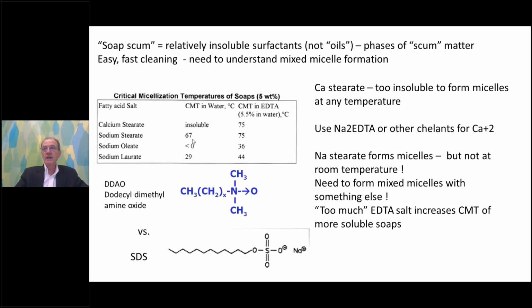So typically we formulate our soap scum cleaning products with some other surfactant because we're trying to form mixed micelles with the sodium stearate that we're trying to produce. And so we might use something like an SDS or an amine oxide. We can't arbitrarily turn up the amount of EDTA either because it's a salt. And if we arbitrarily add too much, we can actually increase the CMT of the shorter chain soaps like sodium laurate or the more soluble soaps like the oleate, which is exactly not what we want to do. So we can't just turn up the EDTA.